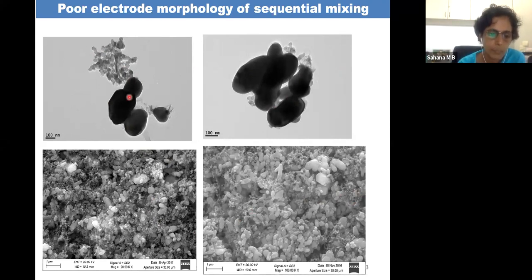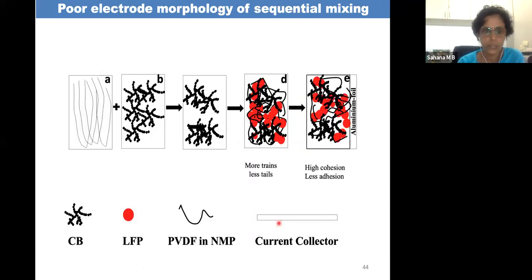You can see here the small particles. This is an SEM micrograph of the electrode. The small particles here are carbon black, and the larger ones are LiFePO4. Especially here, you can see there is no carbon black at all, whereas the carbon black is agglomerated in some places, somewhere here. Now, I'll not go into this.